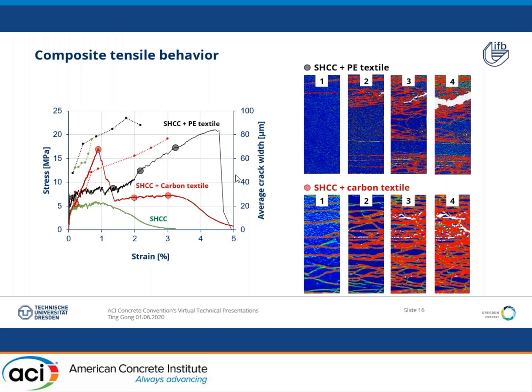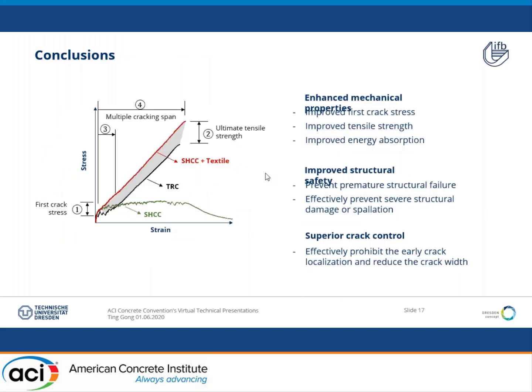When we compare the hybrid-reinforced composites to the SHCC material, we can observe the advantages as concluded here. The mechanical properties are improved with increased first crack stress, tensile strength, and energy absorption. The structural safety is improved by efficiently preventing damage spalling, and the crack control is improved with largely reduced crack width and increased multiple cracks.